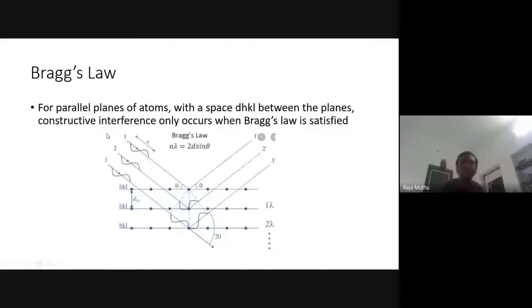For parallel planes of atoms in the space d between the planes, constructive interference only occurs when Bragg's law is satisfied. When Bragg's law is satisfied, you will be getting only constructive interference. What is Bragg's law? n lambda is equal to 2d sin theta. The d is supposed to be lambda divided by 2 sin theta. If the distance is that much, then you will be getting only the constructive interference. Or in other words, to get the constructive interference, you must satisfy Bragg's law. Bragg's law says that n lambda equals 2d sin theta. That's important.